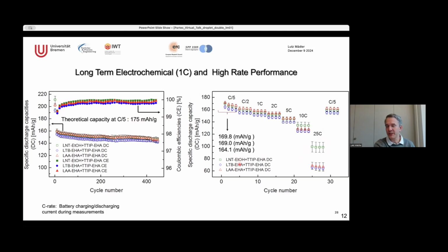So actually we can trace back what we used as a precursor towards what we see in the battery, and the best performing ones are actually those. And the question is, why are these so well performing? And then we couldn't see it in the powder. The powder looked the same, crystallographically highly crystalline, same size.